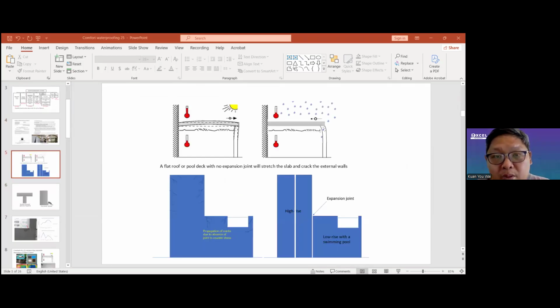So the importance of expansion joints can be illustrated by this diagram. Imagine if your pool or your flat roof doesn't have an expansion joint. Upon expansion and contraction due to temperature, the expansion has nowhere to go but to expand and crack the external wall. When it is cool, it will shrink and pull the external wall. All this can cause the waterproofing to fail, especially if it lacks the elasticity to cater for the expansion and contraction. And as a result, this is what you can see in reality, whereby without expansion joints, buildings have a lot of cracks, and the cracks can crack the waterproofing as well.